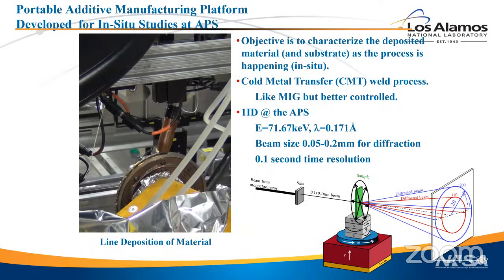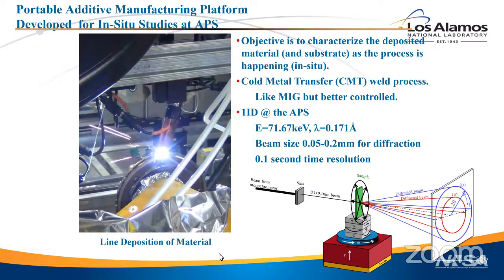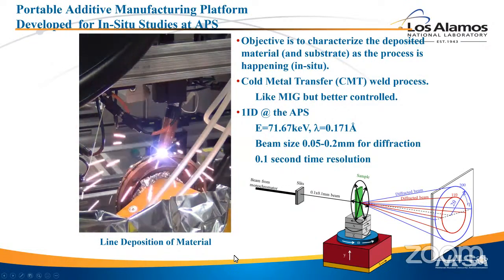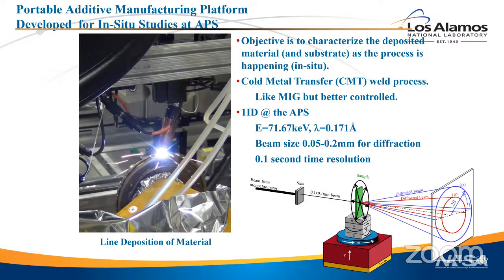So the first example I'm going to give you is in situ wire arc additive manufacturing. This was done at the Advanced Photon Source, and this is the actual process going on. We have a wheel that's rotating, and as it rotates, we're depositing material on it, and we're passing X-rays basically right along into the screen. We pass X-rays through that depositing material, and we collect diffraction data while it's solidifying and cooling, and we can pull out microstructural features while that's happening.